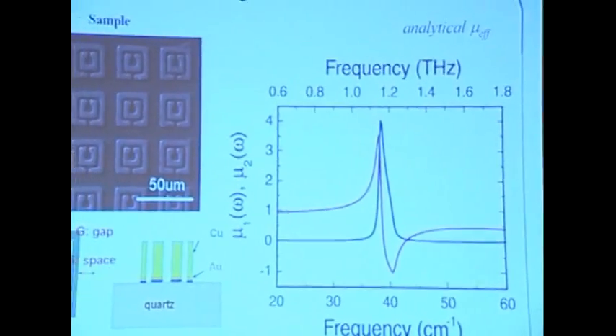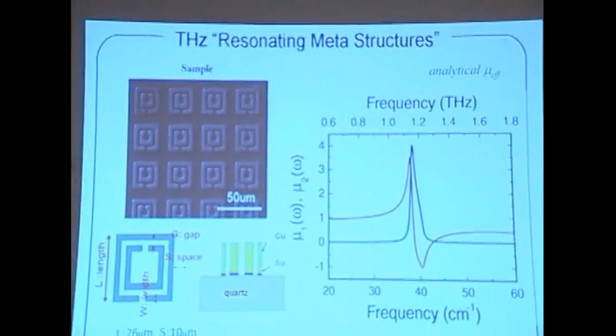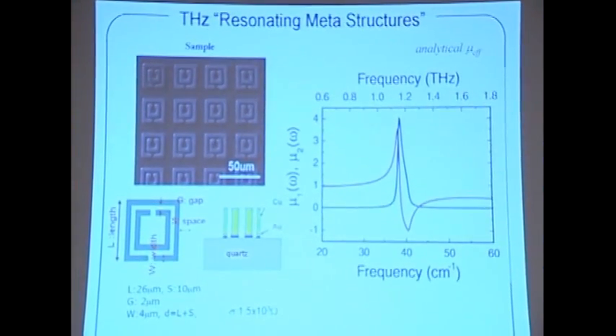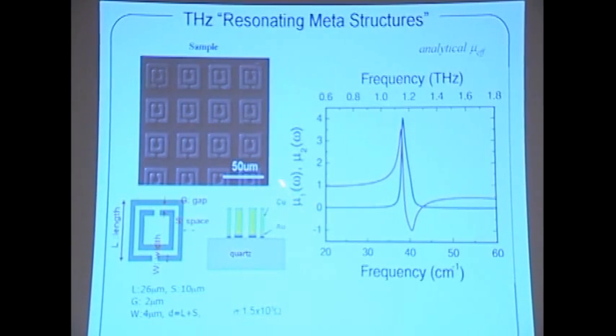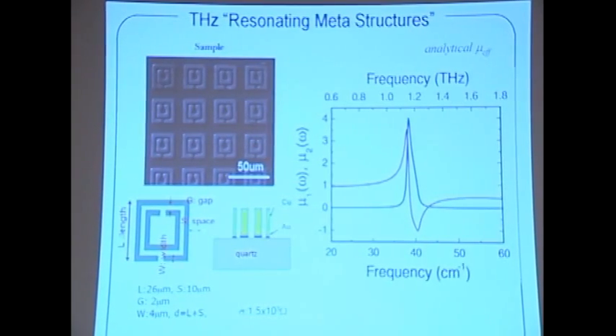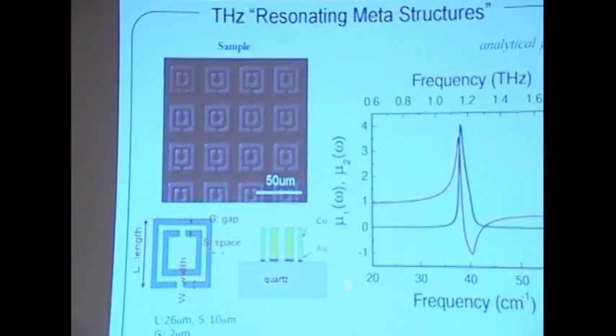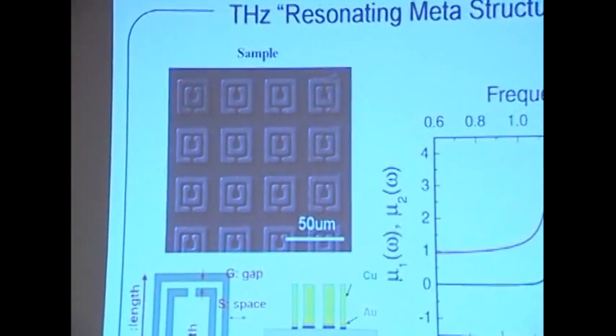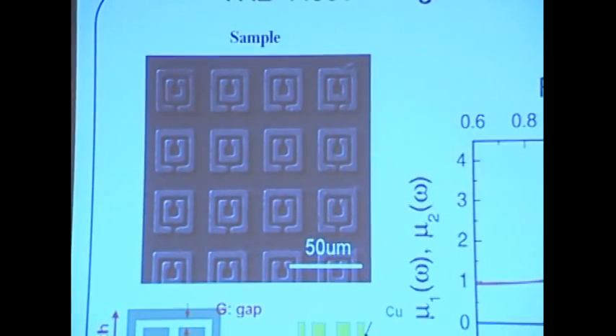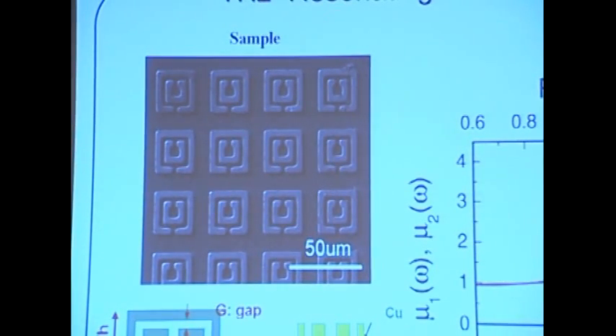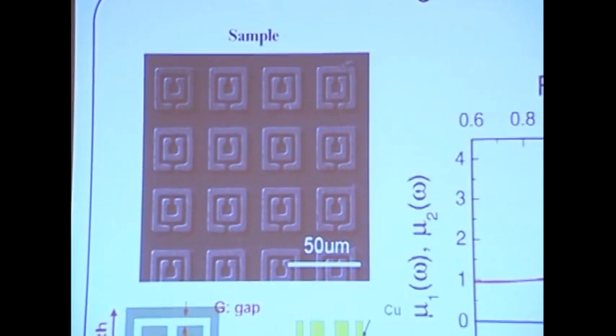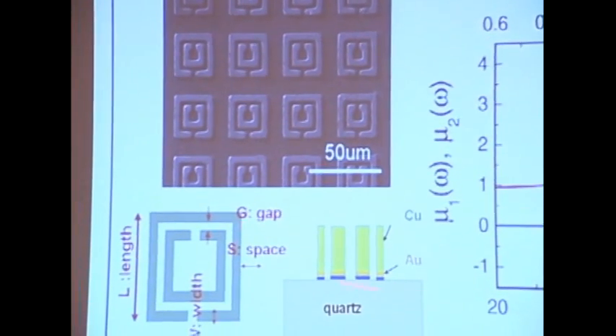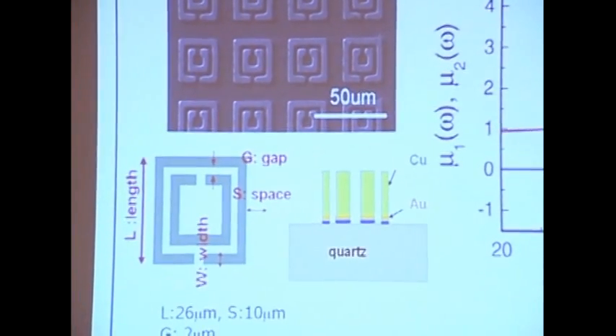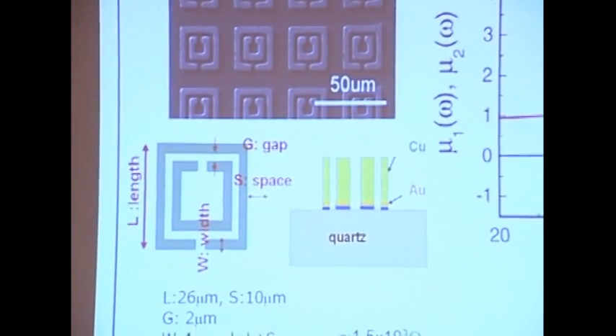So about 5 years ago, we decided to test this interesting theory by fabricating these artificial magnetic structures with copper, for example. Itself doesn't have magnetic response at very high frequency. And we are looking at the terahertz range, where most natural materials don't have any magnetic response. This is basically microfabrication, and each of these atoms is about 26 micron, so it's not small.